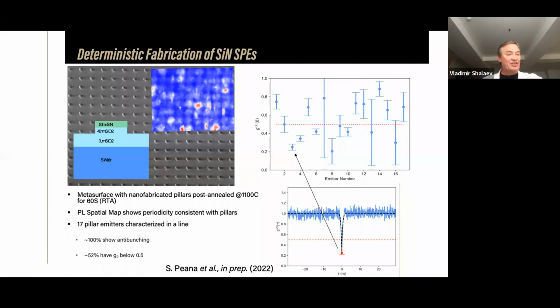We don't have a full explanation, but our working explanation, our hypothesis, is as follows. Remember I mentioned that when you create this silicon nitride, you have to use this rapid thermal annealing. Because the expansion coefficients for silicon nitride and silica, SiO2, are different, you create stress at the interface of the silicon nitride pillars, which are sitting on a silica substrate. And at a certain stress, it results in a single photon emitter. It's stress induced, but that stress depends on the size of your pillar. So by choosing the right size of a pillar, you actually create only one single photon emitter.